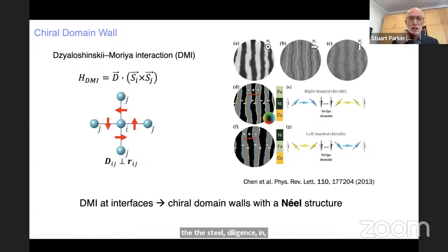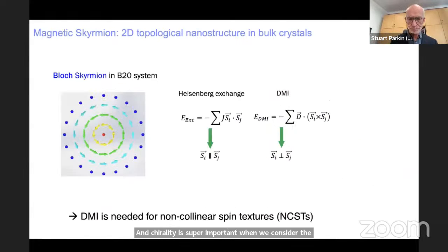But in systems, depending upon the crystal symmetry, the DMI interaction can have different forms, and the components can be different in different directions. Nevertheless, this can give rise, in this particular case, to domain walls which are chiral with a Néel structure. And chirality is super important when we consider the motion under spin-orbit torques of these domain walls.